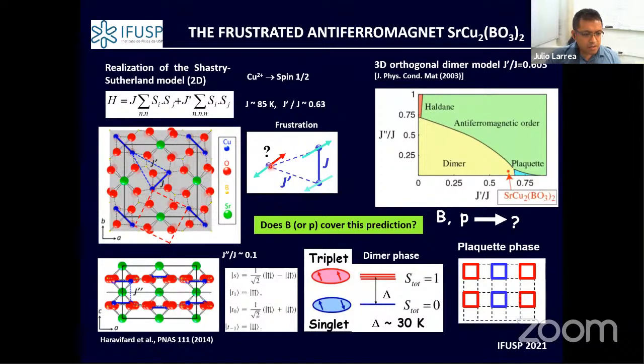If you place another orthogonal singlet as the next-nearest neighbor, for one bond you can still have the antiferromagnetic coupling, however for the other one, not. This creates instability in the stabilization of the spin orientation, and this instability brings what we call quantum fluctuation, or the effect of magnetic fluctuation.